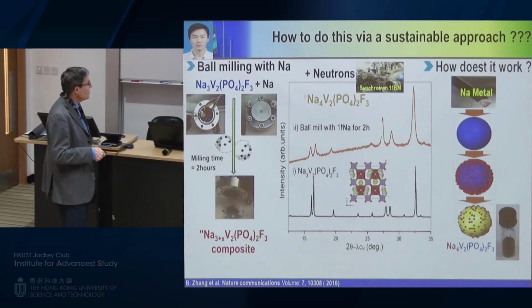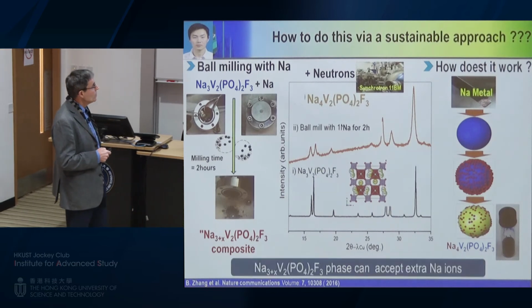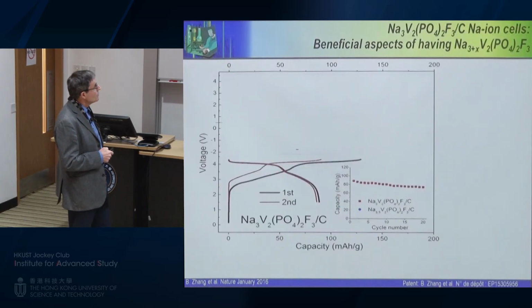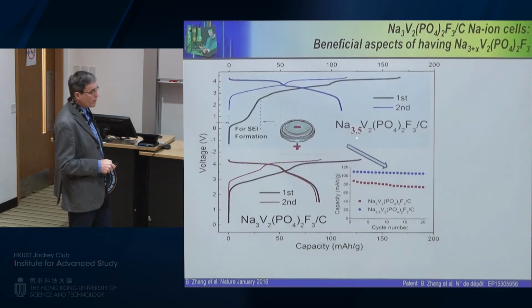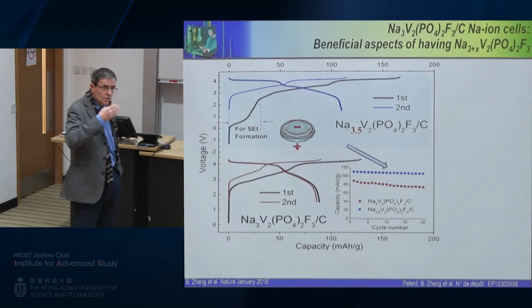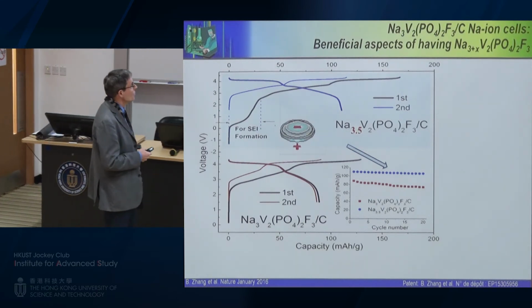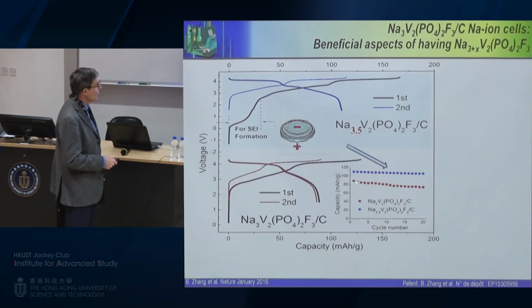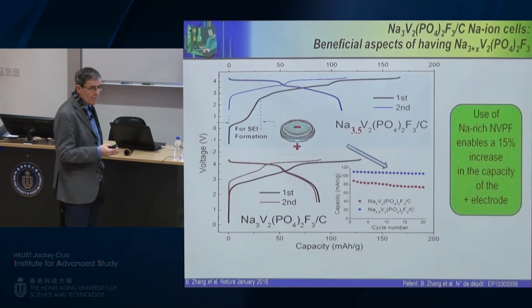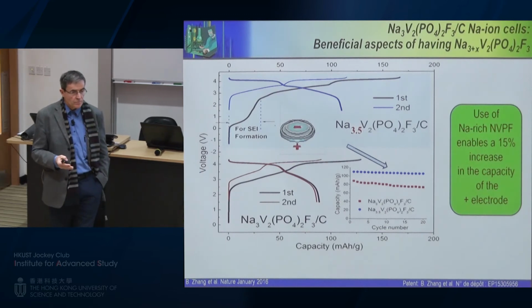So now, with this type of phase, we could prepare some batteries. This is the data from the classical Na3V2(PO4)2F3. Now, when we use the trick of adding sodium, you can see that when we charge this, we remove this extra sodium that is used to compensate for the irreversible capacity I mentioned before. And the result is indicated here: you increase the cell capacity by 15%.